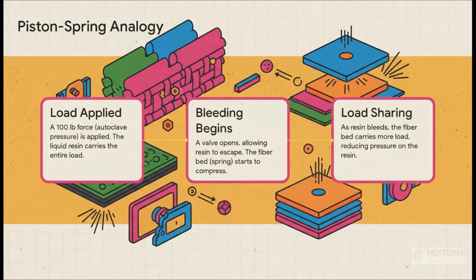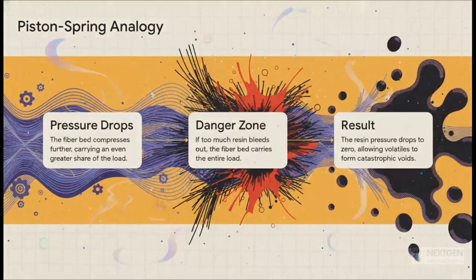To really wrap your head around this, let's use this fantastic analogy. Okay. Imagine the composite material is a piston. It's filled with liquid resin, and there's a spring inside that represents the solid carbon fibers. Now, when you first apply 100 pounds of force, that's our autoclave pressure, the liquid resin is holding up that entire load. But then you open a little valve and let some resin bleed out. As it leaves, the spring, our fiber bed, starts to compress and take on some of that load itself.